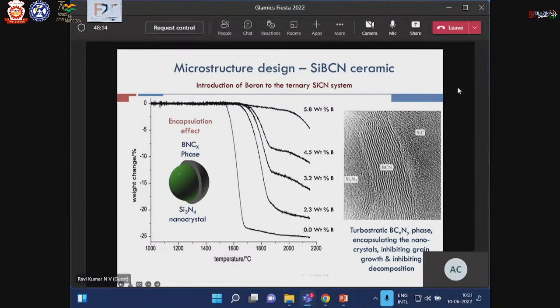A schematic is shown here to show that the degradation of this material, which is primarily controlled by the degradation of silicon nitride, is prevented by this BNC phase. Thermodynamically, one would have predicted silicon nitride degradation, but microstructurally, we could see that such a degradation doesn't happen. Based on this concept, we have designed many materials, and made materials which otherwise would have decomposed, to be stable.